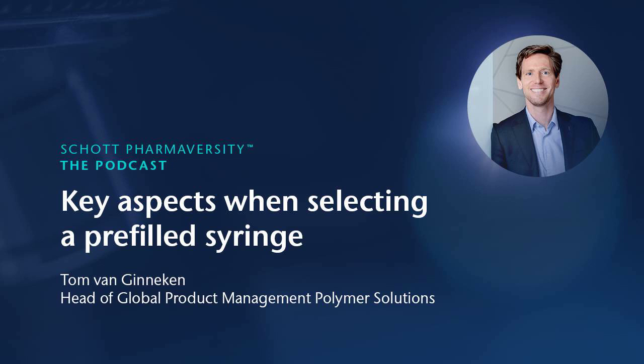Now, with a polymer syringe, this risk is highly minimized because the luer lock is integrated in the injection molding. So there's no disconnection between the luer lock and the syringe. And therefore, you can also twist in the needle really firmly without the needle popping out of the luer lock. In addition, because of the design flexibility that polymer offers, you could develop a syringe with a smaller inner diameter, and this reduced inner diameter offers an easier and smoother emptying of the syringe.